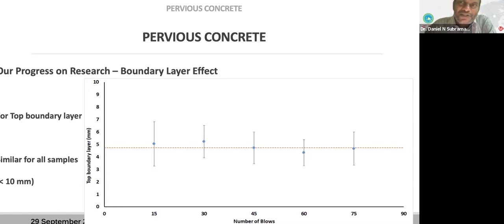So when we are closing the cubes, what we do is we put some more and then we try to flatten it. So that is the effect. We can definitely see that it is not varying with compaction or aggregate to cement ratio. Nothing affects it, and that is about 5 millimeters on the top.